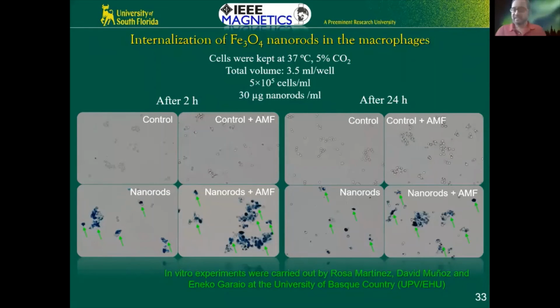Now keep in mind that everything that I told you is only half the story, because whatever material we make in the lab, we need to check the biocompatibility. That's the only way we can go to the next step of actually taking it to clinical trials. So you need to study what is known as cytotoxicity. We do these experiments by feeding these particles to cells. This is an example of a macrophage. We chose macrophages because they are very hungry cells. They will eat all the particles, and the particles go inside the cells, and then you can apply the AC fields to test the functionality.